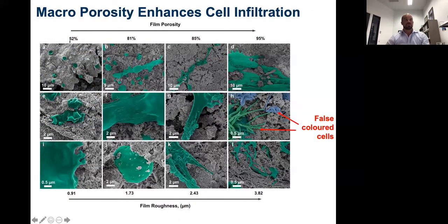So basically this is differences in porosity as we go across the top here. And what we found, and the green here are false colored bone cells growing on these coatings, is that when the porosity increased above 80%, we started to see these bone cells sending extensions, known as filopodia, into these highly porous materials. And you can see them really clearly here where they're growing in, under and through these highly porous materials. And then we're actually seeing these cells remineralizing, which happens in bones when you have fractures and things like that. And we can see them actually mineralizing within that coating. So we're getting that superior fixation to eliminate the need for revision surgeries for patients that have these implants.